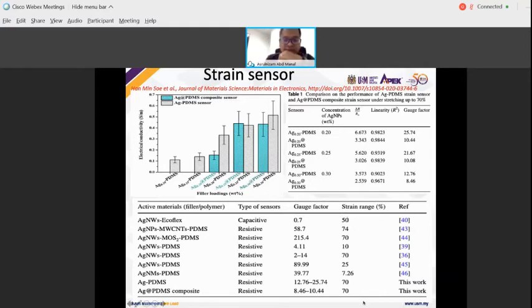This is the gauge factor for the silver PDMS. The value is in the range between 12 and 25, and the stretchability can go to 70%. For the PDMS composite with silver nanoparticles added, the gauge factor is 8.46 to 10.4, and the strain can also go to 70%. So that is one example.